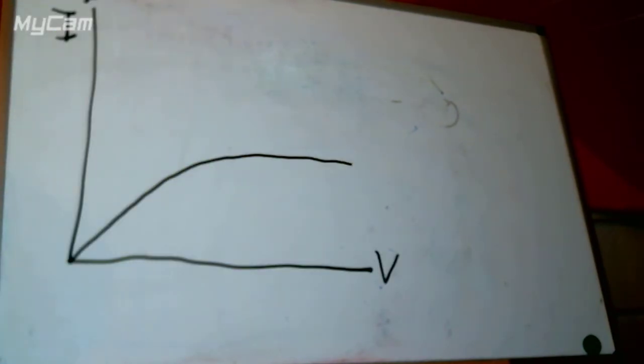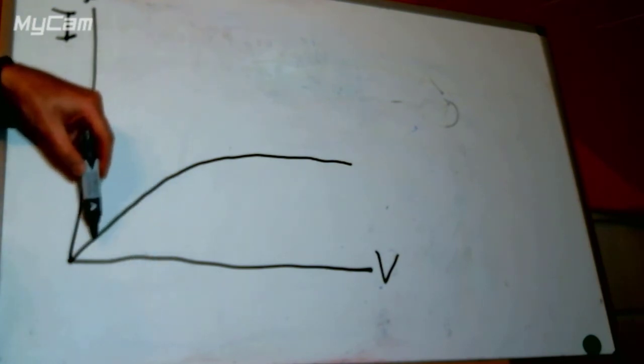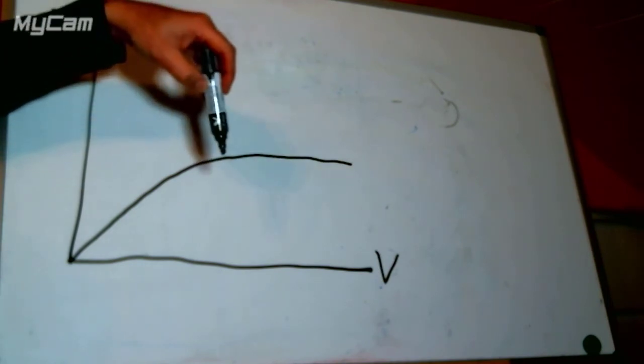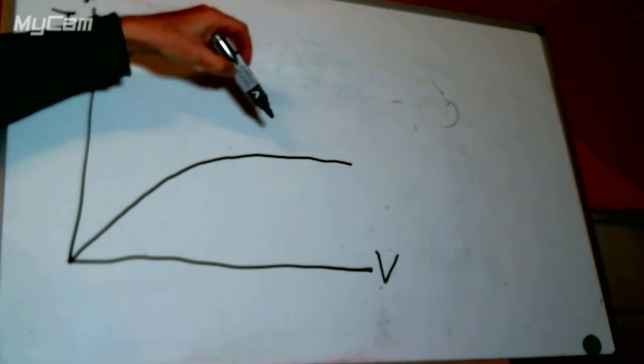So as a last part for today, we will consider just the positive part where we're dissolving copper. So we've got our piece of copper. As we make it more and more positive, it dissolves faster and faster, and then we get to a point where we can't get more copper into the solution close to the electrode, and so it has to diffuse away.